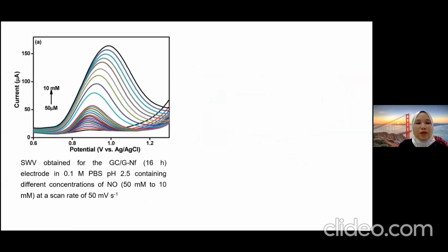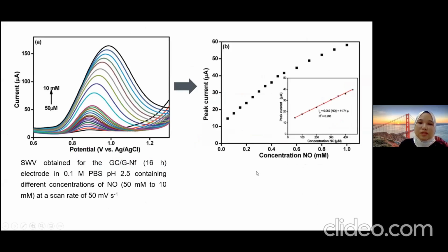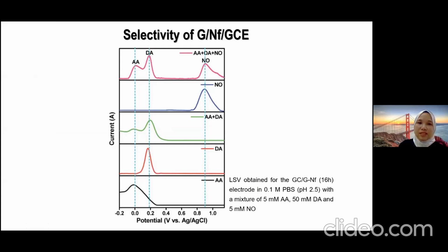Okay, and then we are using the square wave voltammetry to calculate the limit of detection. Right, from the linear graph here, we can calculate the limit of detection due to the increment of concentration of nitric oxide from 50 micromolar to 10 millimolar. So the limit of detection was calculated to be 11.61 micromolar. We also study the selectivity, okay, with the presence of ascorbic acid, dopamine, and nitric oxide.